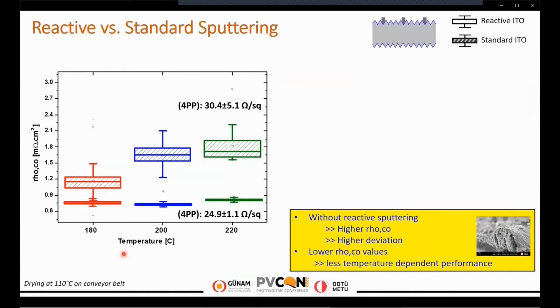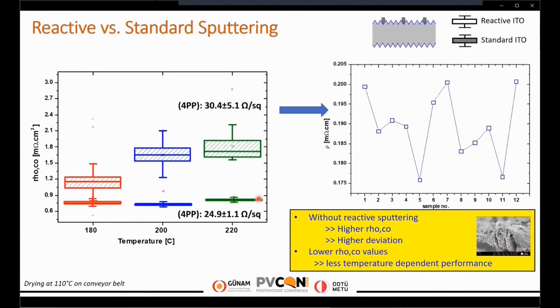When you look at the results for the standard ITO sputtering, contact resistivity values are higher than 1 milliohm centimeter square. The results have higher deviation compared to reactive ITO sputtering. For the reactive ITO sputtering, all contact resistivity results are below 1 milliohm centimeter square. So without reactive ITO sputtering, we achieved higher contact resistivities, and with reactive ITO sputtering, the deviation in the resistivity values decreased, and we have achieved less temperature dependent performance of the metal contacts.